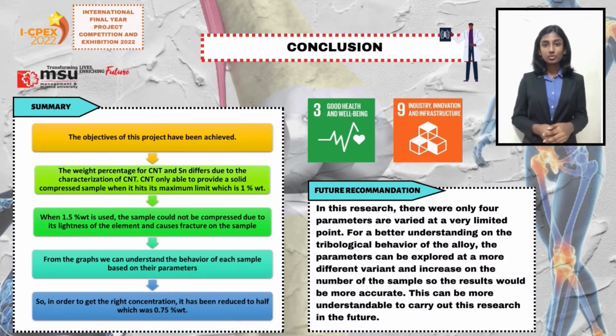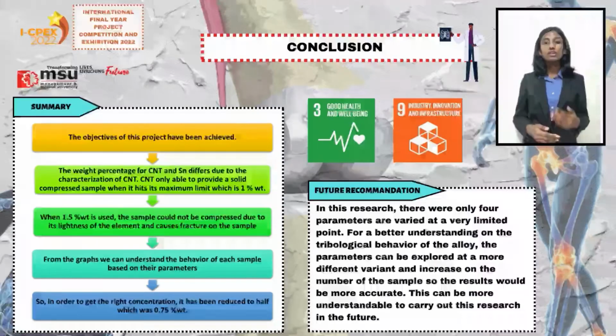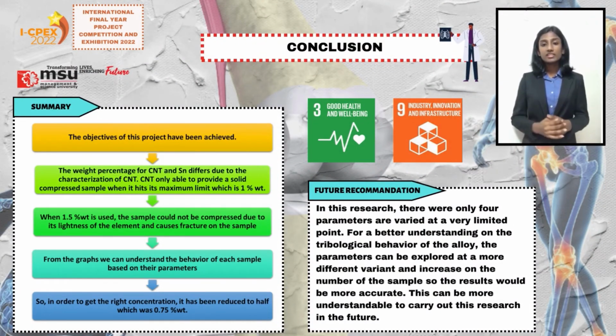Through the 3D microscope, we can see and measure the depth of the wear that has occurred after the ball on disc has penetrated during the wear test based on the variables that have been set in the design of experiment. This project aims to develop a sustainable porous titanium shape memory alloy that is safe, effective and high quality for use by both older and younger generations without having a long-term effect. In addition, carbon nanotube and tin act as novel additions to the world of biomedical.